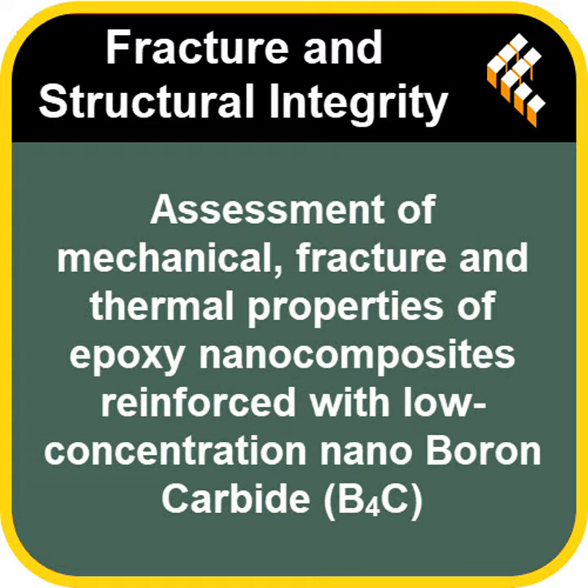Very interesting. Now, these are all experimental results. Did they do anything to sort of double-check them computationally? They did. They used finite element analysis, FEA. They built these computer models called representative volume elements, or RVEs, to simulate the material's behavior and predict its properties. And the good news is, the simulations generally matched the lab results quite well. For both tensile and flexural properties, the difference between the experimental numbers and the FEA predictions was mostly within 15%. That gives us more confidence that the effects are real. Though it's worth noting the simulation assumed perfect particle dispersion, which is likely why it predicted slightly higher tensile strength at 0.4% than what they actually measured, because it couldn't fully capture that real-world agglomeration effect. Right, models have limits. But the agreement is still pretty good.